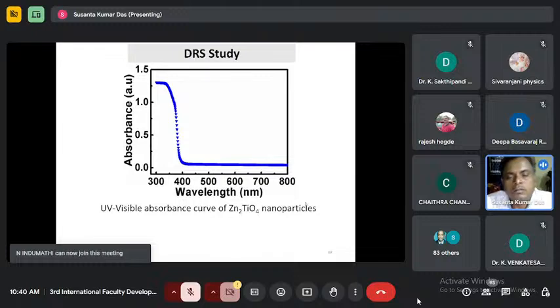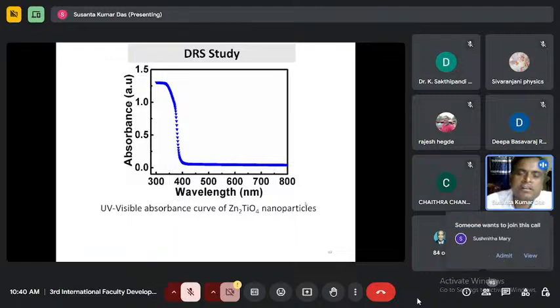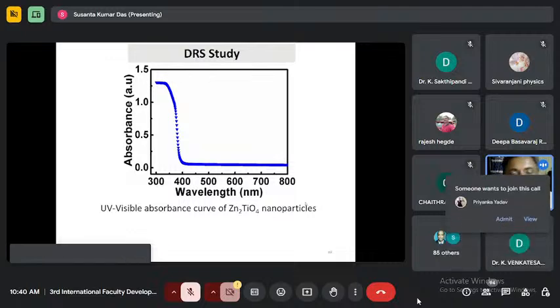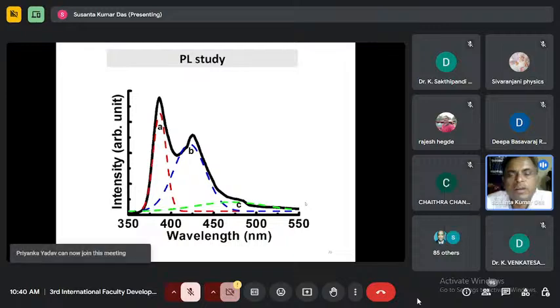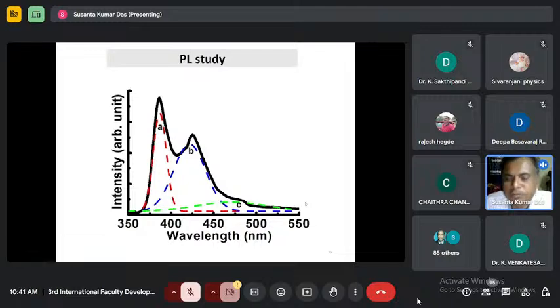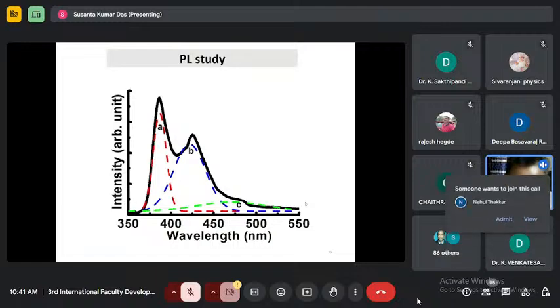Then we went for other studies like diffuse reflectance spectroscopy to know the band edge absorption, and it was coming similar because both of the materials have a large band gap. And we did the PL study also, but in this case the defect was found to be more. So that means the defect absorption was there, and that was found to be more useful in our visible photocatalysis. I'll show you later.